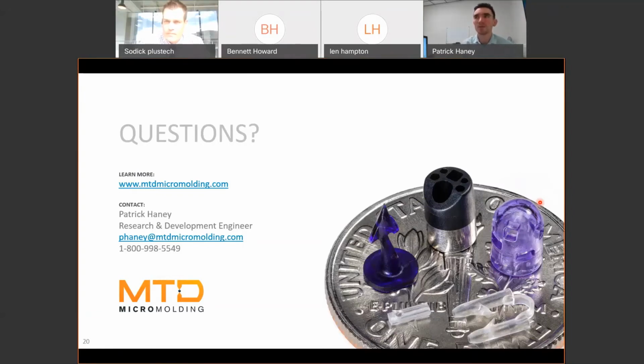Right, yeah. So, a lot of questions like this, this is something that makes the plastics industry pretty interesting, right? Because questions like this kind of depend on what type of polymer you're working with. So, shear heating actually has a greater effect on a drop in viscosity than just ambient temperature does. So if we have heater bands on our barrel, right, then that will affect our viscosity and the drop in viscosity less than exposing it to shear rate.